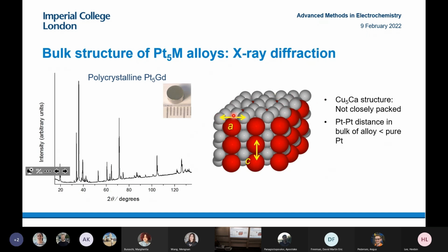We have one platinum layer and then one layer of the platinum and the rare earth. This one looks like a close packed layer, but it's not. And we have little holes above the rare earth. It's called the kagome structure, from Japanese.